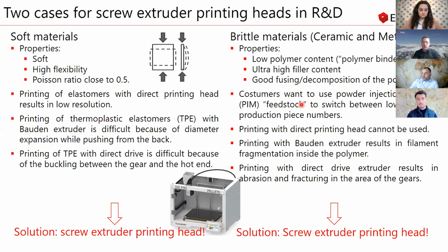And very often the consumer wants to use a feedstock. A feedstock is a material which consists of ceramic or metal powder and a polymeric binder. And this has already been used quite a lot for powder injection molding. So it would be great if we can use powder injection molding feedstocks also for 3D printing. With a direct printing head, this is clear that it cannot be used. Bowden extruder, also clear, and also with a direct drive extruder, the problem is that these materials are typically so brittle that they will fracture or have high abrasion at the area where we have the gears.